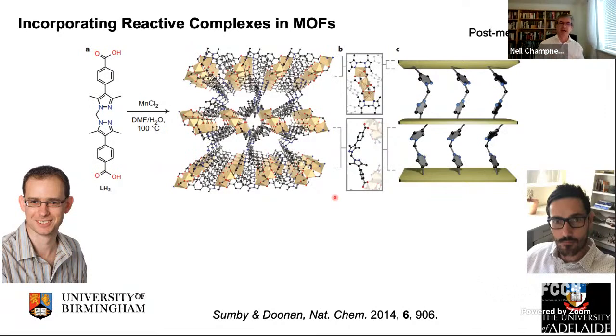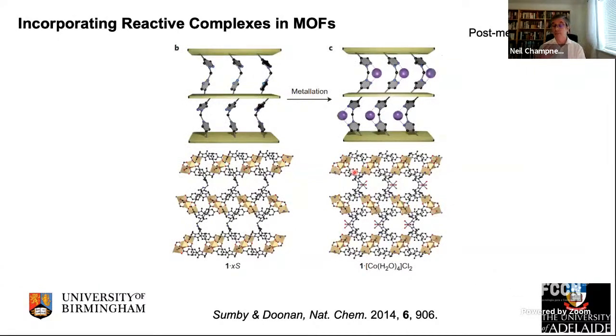So the MOF structure is very complicated, actually. But the important thing is it has these pores, and adjacent to the pores is a vacant binding site. So you can see this here. This is the bis-pyrazole site, and it's sitting adjacent to a pore. And what they showed was that you could take these MOF crystals and you can metallate those vacant binding sites. And so this is a simple example where you just take the crystal of the MOF and you suspend it in a solution of your metal complex, in this case cobalt chloride. The cobalt chloride diffuses into the framework and binds the vacant binding site. And actually you can do this with, this paper has rhodium complexes in it as well, and you can do it with a whole variety of different metals.